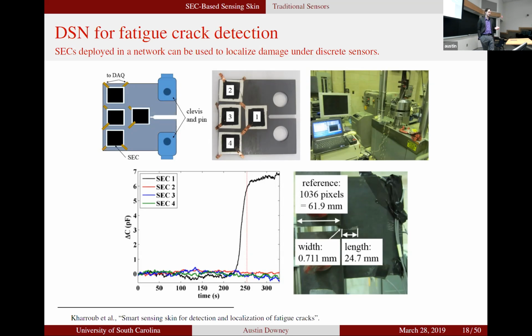Right. If you already have a crack on that beam and that crack is static and not growing, you won't see anything. But one of the issues that raises is where is that crack going to grow to? If you have a fatigue crack that's growing and you put a relatively short gauge length strain gauge on it, like a resistive strain gauge, that fatigue crack may grow around it. In this situation, you can put a sensor on that's very large, and as long as that fatigue crack grows in any direction, you'll be able to detect it. But you'll only be able to detect the changes after that point, which is why it's important to detect damage early on, because it allows us to gather that data for a prognostics type view looking forward.